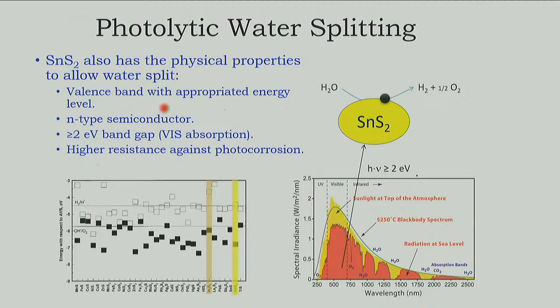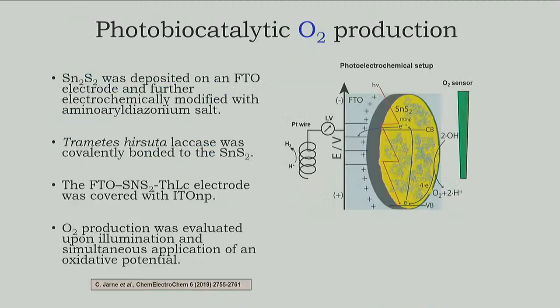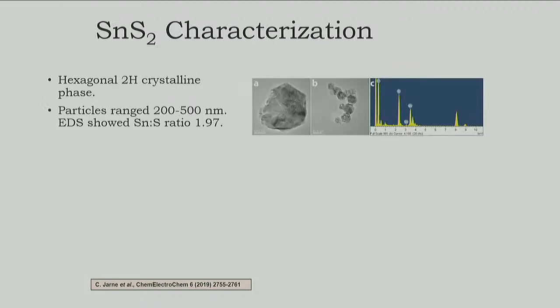It's also an N-type semiconductor that is good for these applications. Okay, so exactly the same system, but in this case we also implement here indium tin oxide nanoparticles, because we were scared that these particles, which are like 100 nanometers, the enzyme are much smaller, they are going to sit and have not very good connection with the electrode, so we have to fill it with something. So in this case we tried ITO nanoparticles that are 30 nanometers to fill in the gaps between the semiconductor and the electrode.